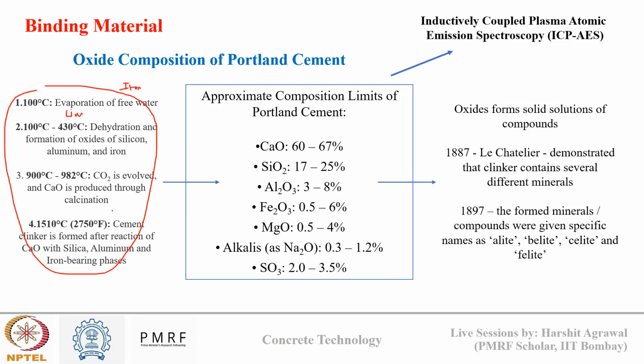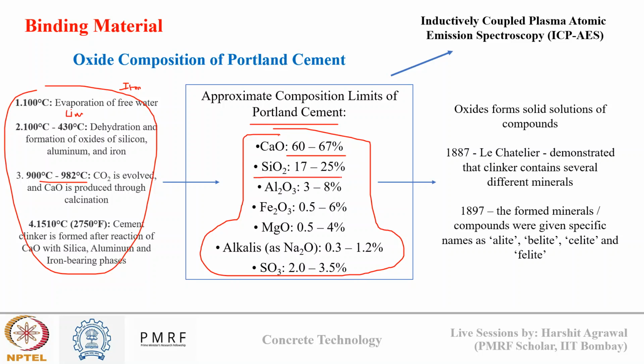For general Portland cement that we get in the market, the composition of oxides present in the clinker is of this order. Calcium oxide is around 60 to 67%, silica oxide is around 17 to 25%, alumina oxide is 3 to 8%, iron oxide is 0.5 to 6%, and magnesium oxide is 0.5 to 4%. There are alkalis present, which are 0.3 to 1.2%, and sulfates, SO3, present in the range of 2 to 3.5%.